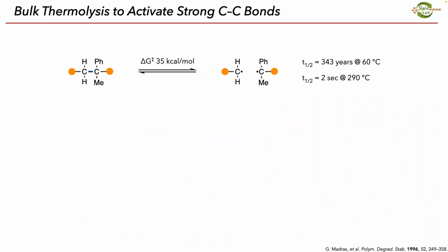And so just thinking about bulk thermolysis of carbon-carbon bonds, if we look at this CC bond here, which is from poly-alpha-methylstyrene, it has a high activation barrier. And so you need to pump in a lot of thermal energy to break or homolyze that carbon-carbon bond. And so if you heat this up to 60 degrees, it'll take 343 years to break half of those carbon-carbon bonds. Obviously, that's not going to work. However, if you heat it up to 290 degrees C, now you can break those down in just a few seconds. And then if you start generating those radicals, then it can depropagate and form monomer back.